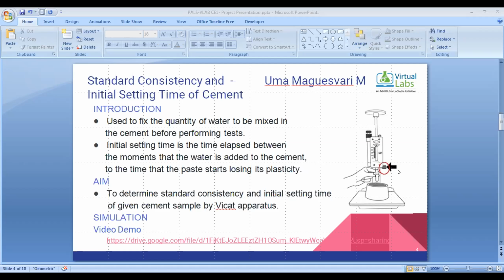Suppose the reading is between 33 to 35 mm. That is the percentage of water, and that percentage of water is the standard consistency. Initially it will not come, so we have to do some trials by increasing the percentage of water, like by 2 percent, until at some percentage of water it comes. That is the standard consistency. That is the input for the other tests, like initial setting time, soundness, compressive strength. But here we are seeing another test, that is initial setting time.